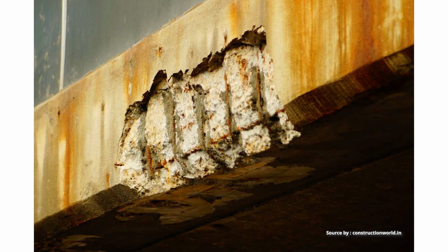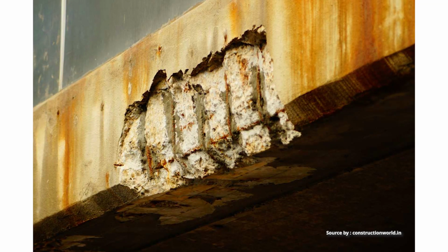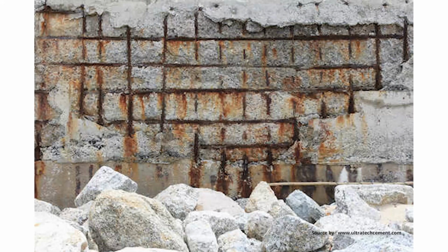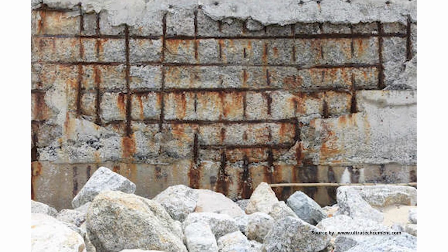But again, at some point corrosion occurs. And once corrosion starts, the corroded steel, the red rust, takes 4 times more volume than the healthy black steel. This increase of volume will open up cracks, bringing more oxygen and more water, which literally makes the corrosion phenomenon exponential and therefore causes big damages.